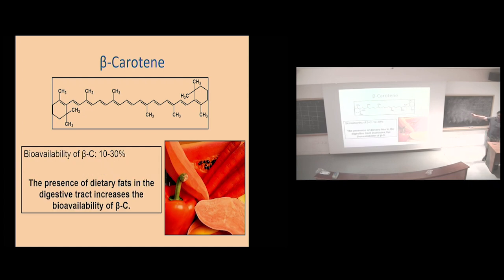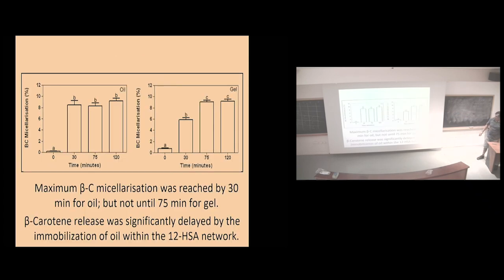So beta carotene is the orange component in carrots, right? And what we did is we put it in a hydroxystearic acid oleogel. We're just looking at applications, hydroxystearic acid, and we did an in vitro test. Imagine you have some sort of emulsion with the hydroxystearic acid and the beta carotene in there, and we hit it with an enzyme, and the enzyme starts breaking down, and outside it's a surfactant, and the beta carotene goes from inside your emulsion to this micelle. I forget what surfactant we used. But it's beta-carotene micellization, and it becomes redder and redder as the enzyme degrades it, and it leaves your little emulsion.